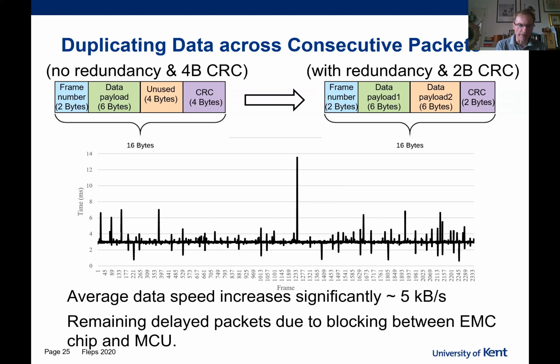And you can see here from the measurements that the number of packets taking 6 milliseconds to arrive has been considerably reduced. Those remaining longer transit times we anticipate are caused by the remaining blocking, which is instigated at the tag to avoid memory loss or data loss. So now with this system, the average data speed has increased significantly, and it is now arriving at the sort of expected 5 kilobytes per second.